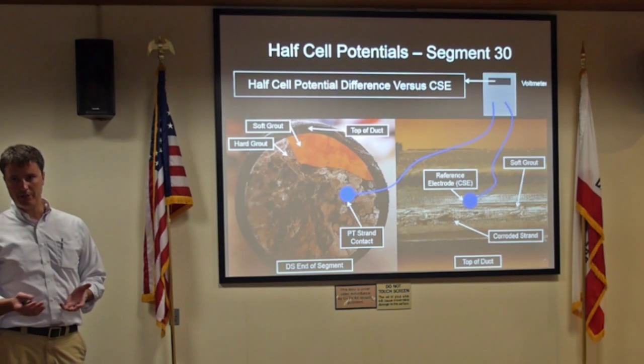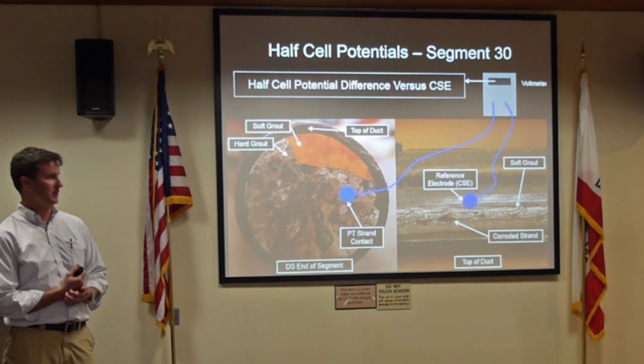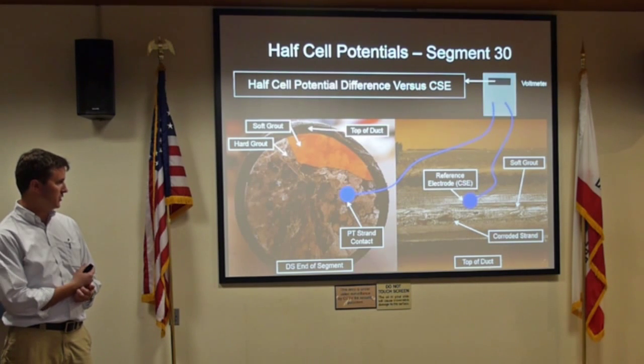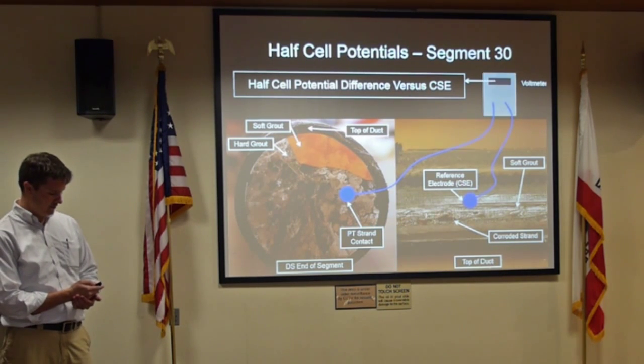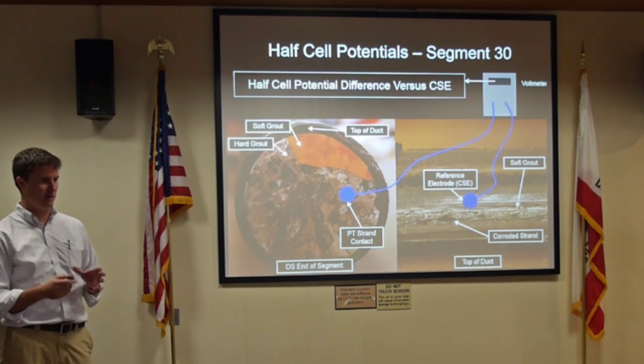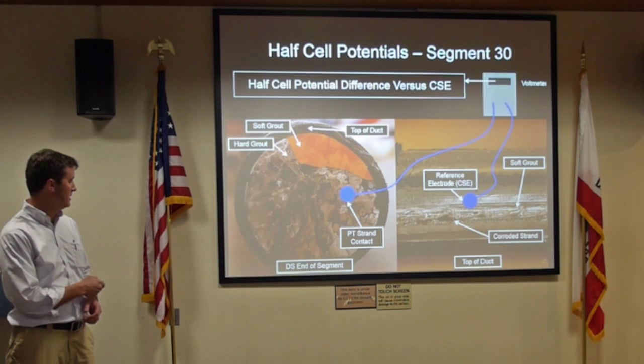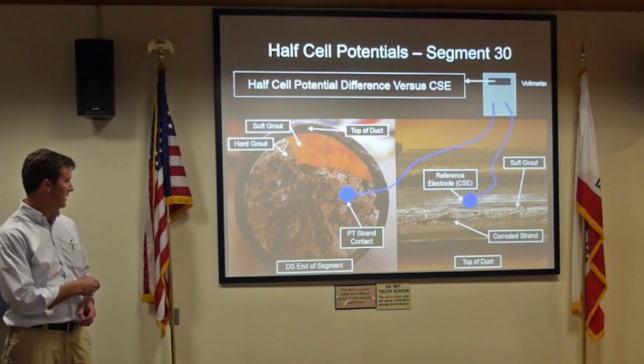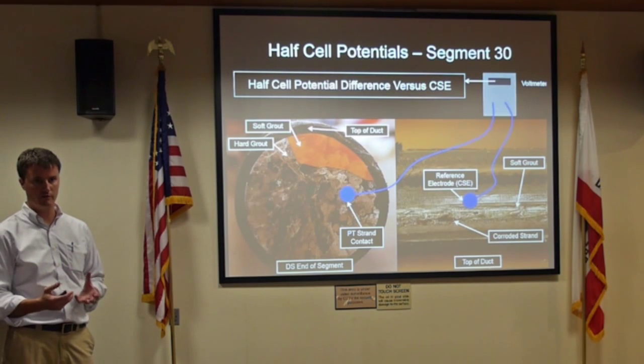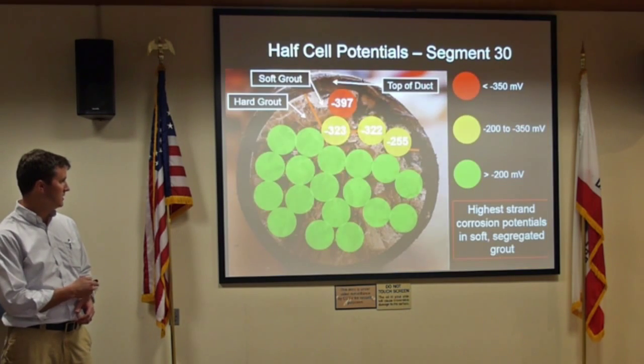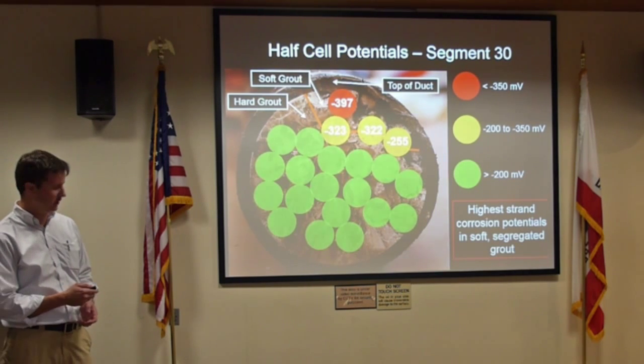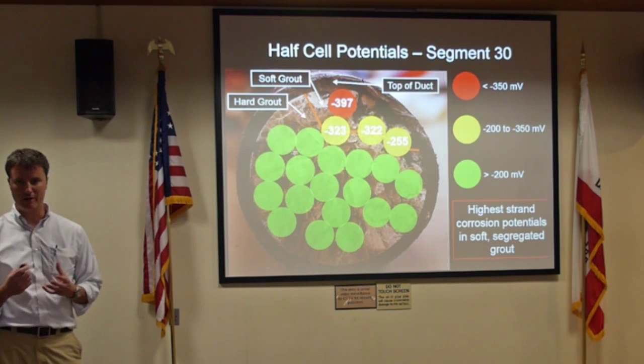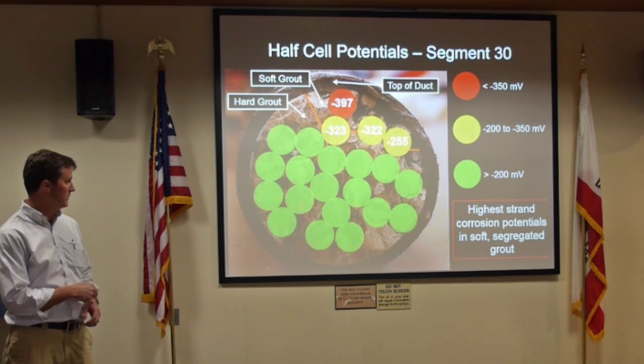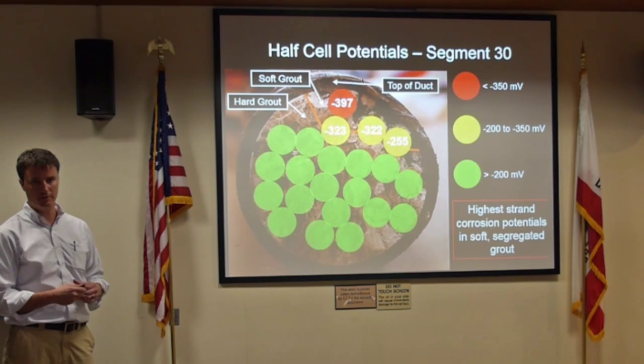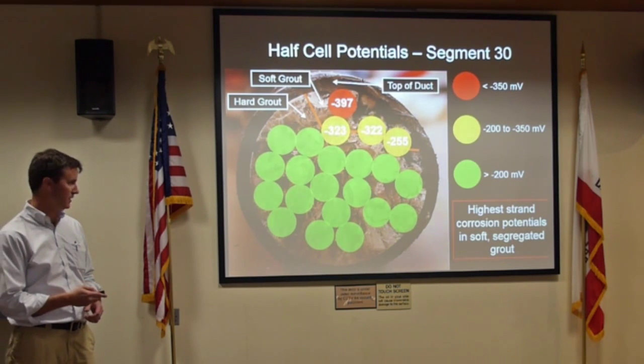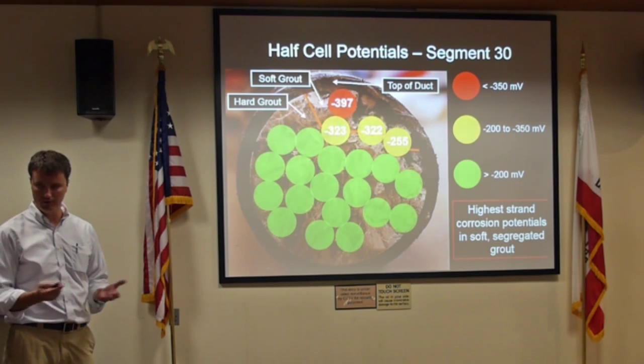So we utilized half-cell potentials, again similar to what we use for reinforced concrete. We connected to the strand as well as to the grout. Looking at this cross section, you can see how the steel is corroded in some areas and appears to be in good condition in others. We identified, essentially just looking at the cross section, an area that appeared to be soft grout or kind of raw material right here. And we found an increased potential as you get into the soft grout, so it looks like an environment that's more conducive to corrosion. But as you can see, about 80% of the strands in this area are fine and are not in a corrosive environment. And if you were to take them out of that tendon, they would look like the day you installed them.